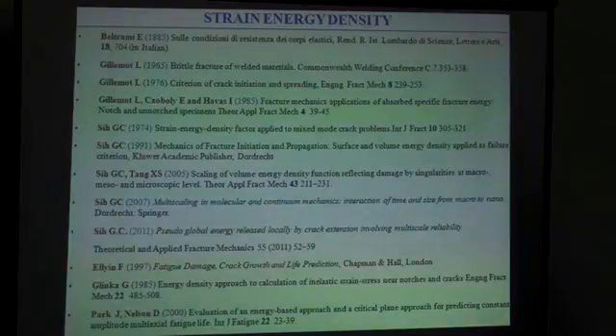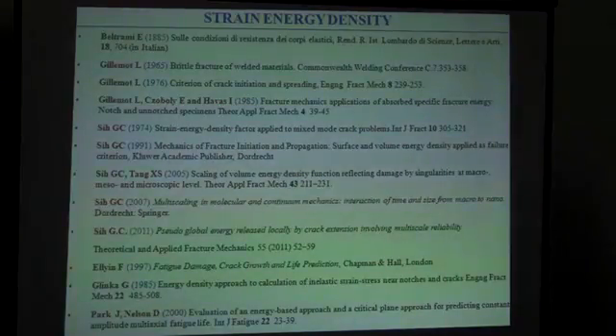Dealing with the strain energy density, we have also some good contributions, in particular the first to use the criterion was Gillemot in 1965. Previously, an Italian researcher, Beltrami, proposed the total strain energy density as fracture assessment parameter, and later there are very important contributions due to Glinka and Park and Nelson later.